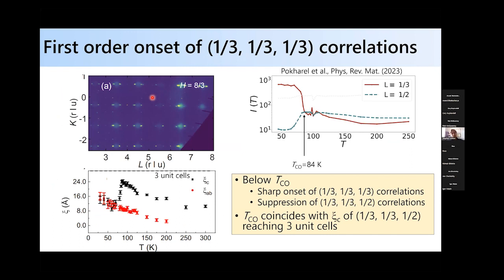Okay, and if you look at the plane in which you can see correlations associated with the root 3 by 3 structure, you see these sharp long-range peaks, and these turn on in a first-order-like fashion. So if I look at the trade-off between the diffuse scattering intensity at the third a half plane versus the diffuse scattering at a third, you can see that basically the correlations are present at high temperature. They increase slightly in intensity, and then once the long-range order turns on, you see a rapid suppression in the third a half wave vector.